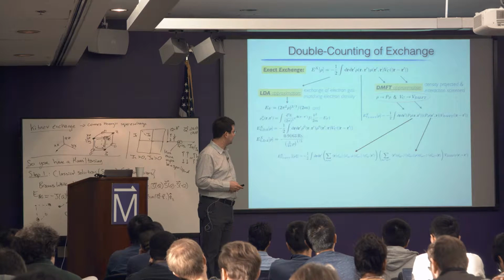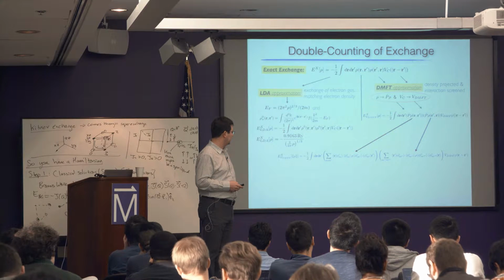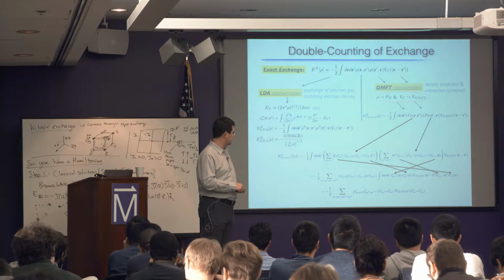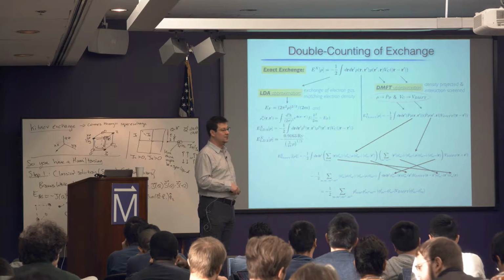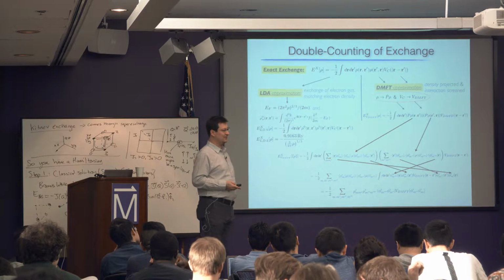Just renormalizing the density interactions, right? No, no, this has everything. Sorry, this has everything. You see, this has different indices, M1, M2, M3, M4. So it has Hund's coupling, it has F2, F4, F6 in general. I mean, all the Slater integrals.